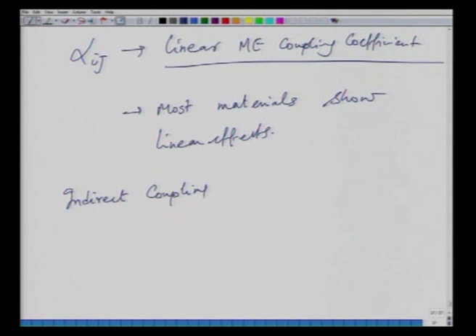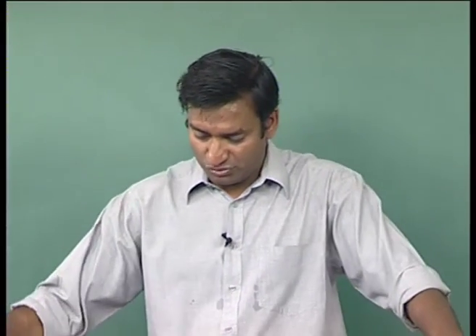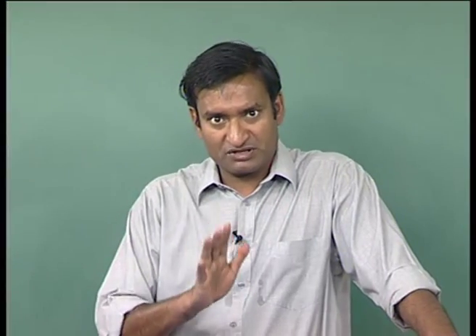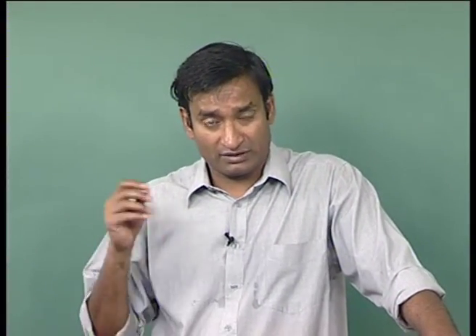There is direct coupling and also indirect coupling mediated by another order parameter such as strain, shown in systems like europium titanate and strontium manganite. Measurements can be indirect — observing fluctuations in dielectric properties near magnetic transition temperatures or vice versa — or direct, measuring the magnetic or electric response of the material directly in response to applied electric or magnetic field.